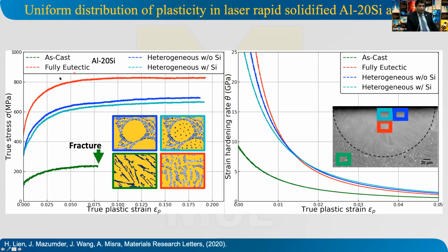That's the best behavior we are seeing, the strongest material, but also high strain hardening rate, which leads to stable plastic flow. I think that's the key part, as you see in this slide, that shows the strain hardening rate is very high, that prevents flow localization. It prevents strain from localizing at the onset of yield. So the entire sample can begin to yield.